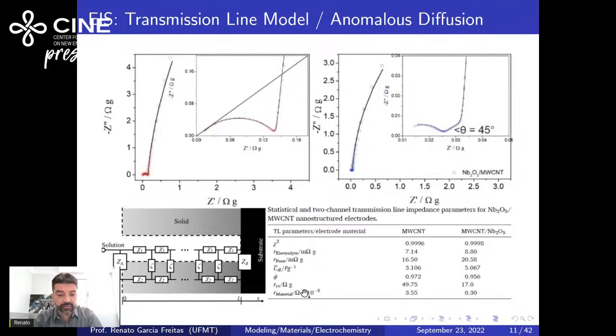A large decrease in resistance, the charge transfer resistance, as you see, 49.75, 17.0, and one order of magnitude decrease concerning the resistance of material. Take a look, 3.5 and 0.3. It's massive. It's massive. That's because it's possible to use this material here, which is niobium oxide, multi-walled carbon nanotube, as battery and as supercapacitor as well. All right?